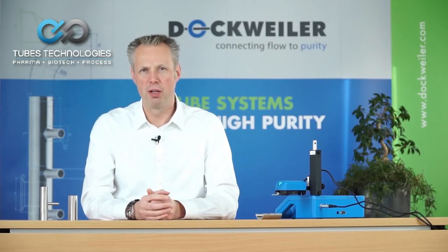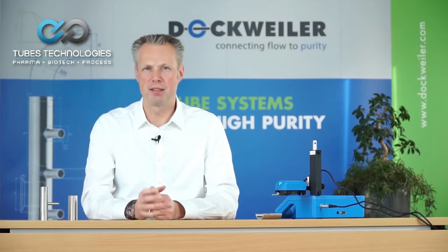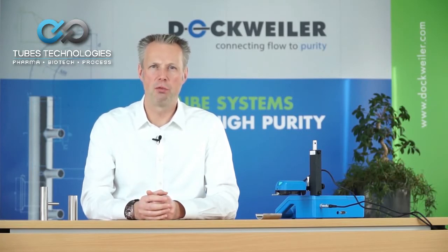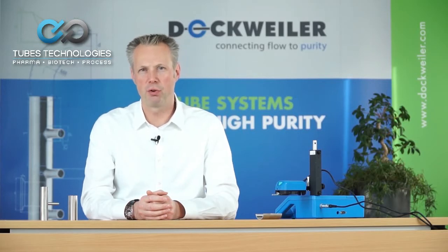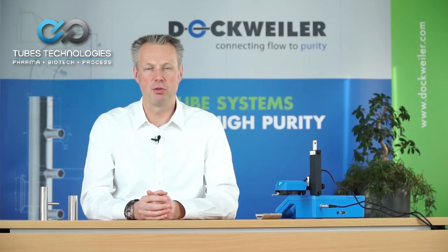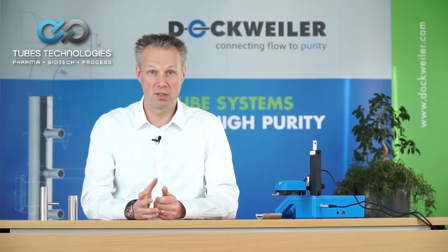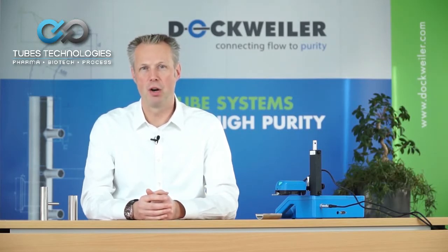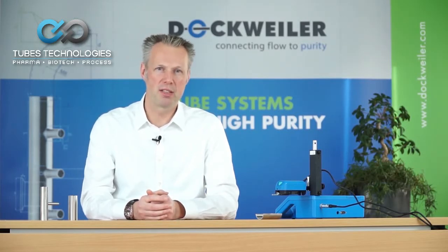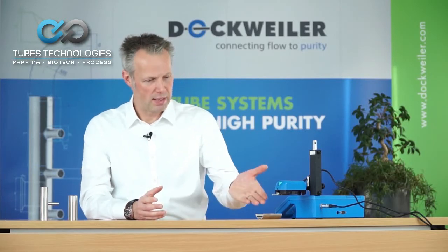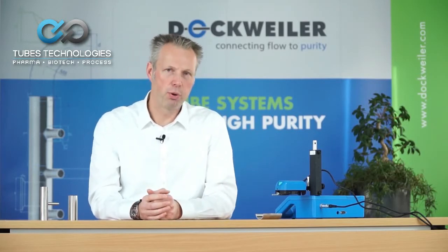Plus, the diamond tip has roughly a diameter of 1 micrometer and it's touching the surface with a force of roughly 1 millinewton. This creates a tremendous force and tremendous impact on a metal surface, especially when you consider the different hardnesses of a diamond and of a stainless steel surface, or a stainless steel electropolished surface such as this one here.